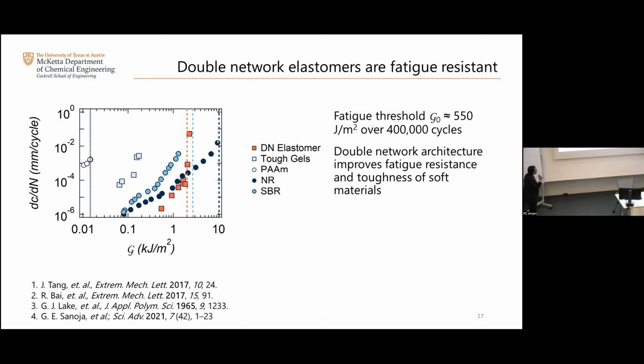So the first observation that I want to show you, let me see how I'm doing time, is the following. What I'm showing here is, how do these systems behave at the macroscopic level? Let's first try to see how they compare with the other systems that I presented before. So in orange here are my double network elastomers. And the first observation that we think is very interesting is that, even these double network elastomers, my fatigue threshold, or effectively the minimum amount of energy that I require to grow a crack during fatigue, is pretty high.